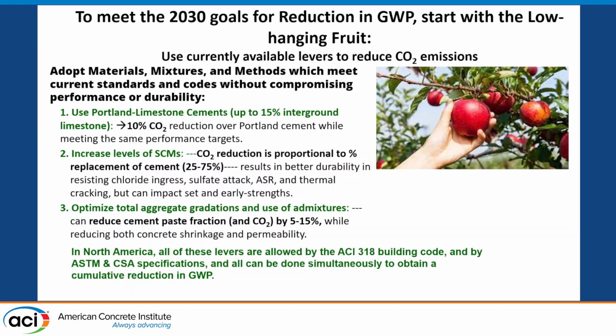You can increase the level of SCMs. Fly ashes and slags have been used for years, but typically at lower replacement levels. A lot of DOTs limit the maximum SCM level to amounts that don't allow you to optimize and reduce further, but you're getting a direct reduction in proportion to what you're replacing with the clinker.